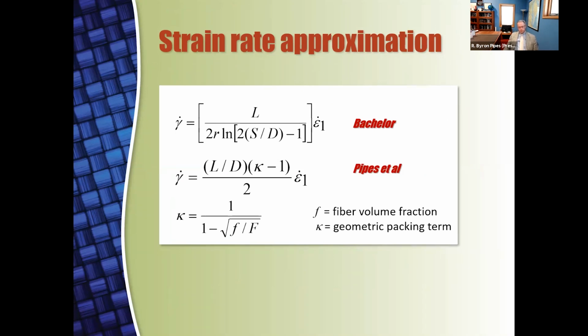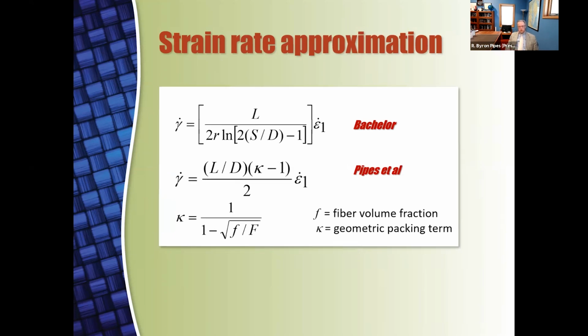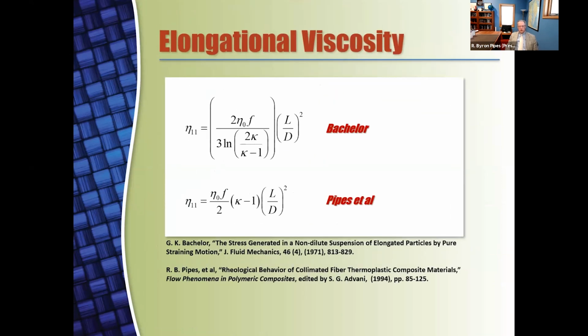There were two of us who had worked on this, and Batchelor had done it. A very famous fluid mechanician had actually studied this in the 70s. I was unaware of his work and didn't discover it till after I'd finished our own work. And it turns out that the two solutions were very similar. They produced viscosity predictions, both of which depended on the length to diameter squared, meaning if you have a length to diameter of 10, it scales your viscosity by 100. If it's 100, you can do the multiplication for yourself.